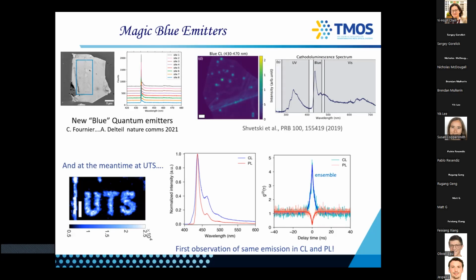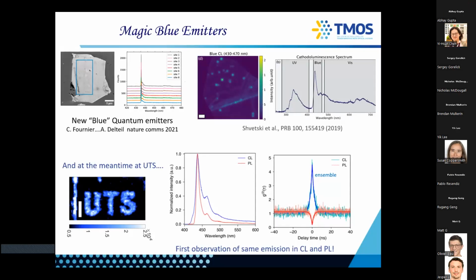You can also see them both in photoluminescence and cathodoluminescence. And when you see a defect in both, it is really good, because it means that you can excite at both sub-bandgap and above bandgap. In cathodoluminescence, you just bombard your material with 30 kV or however much your CL system has, and you still see exactly the same line. Of course, from a single emitter you would see anti-bunching, and there is a lot of discussion in the literature about why you see bunching in CL. We can talk about it offline, but it's just a pretty picture.